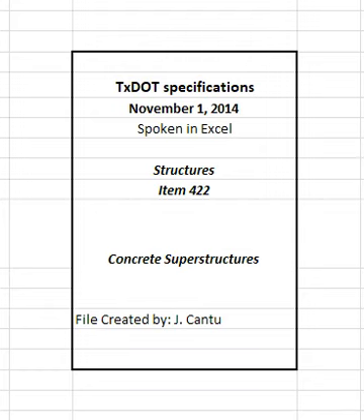4.6.5 Preparation of surfaces. Thoroughly wet all forms, precast concrete panels, T-beams, slab beams, and concrete box beams on which concrete is to be placed before placing concrete on them. Remove free water from the surface or beam lines before placing concrete. Provide surfaces that are in a moist, saturated surface dry condition when concrete is placed on them. Ensure the subgrade or foundation is moist before placing concrete for bridge approach slabs.